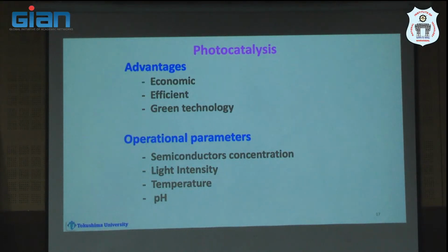But more concentration is not good. It should be less, so that less material can give better performance for a bigger water quantity. So the concentration of semiconductor material, or let's say photocatalytic material, is important. We have to choose a certain percentage. It may be 3%, 5%, or even 10%, but not 50%. That will be too big.